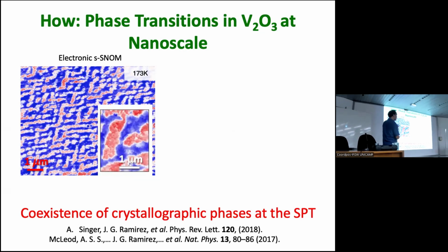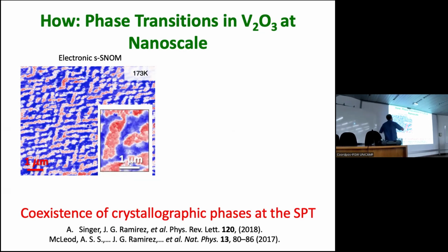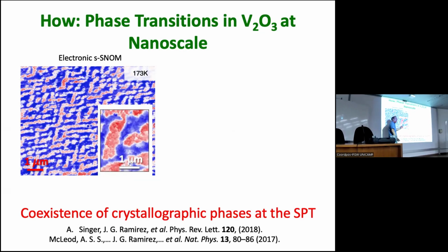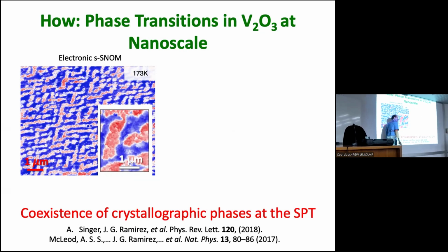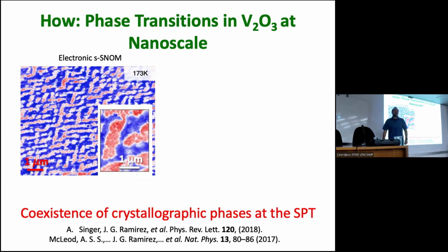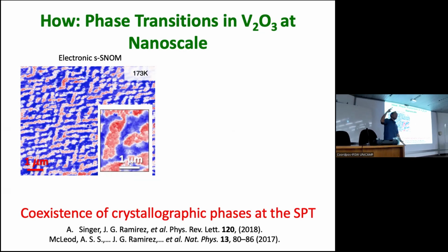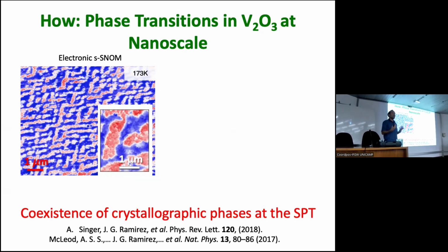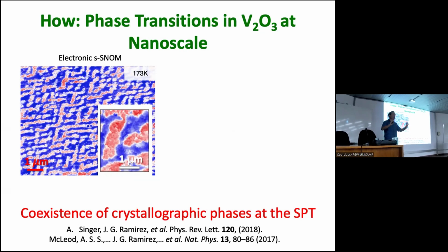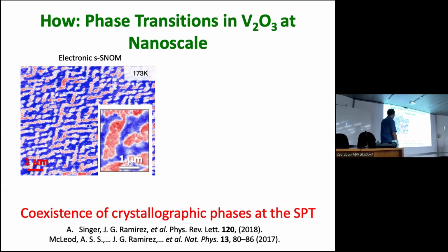So this is a close up. You can see the domains. We studied all the things that you can imagine here. We studied the perimeters, we studied the correlation length on the domains, we studied how they change and change the thickness of the sample. Because this is somehow a percolation kind of effect, we went from 2D to 3D percolation systems. We did all of that, and everything points to a percolation phase in this material.